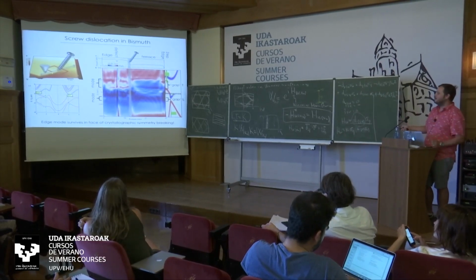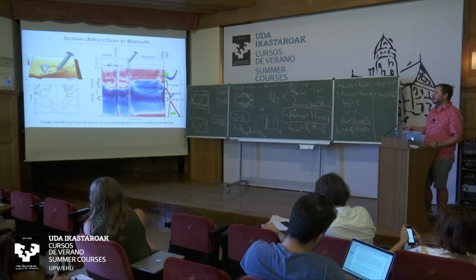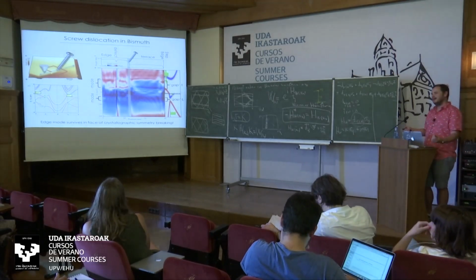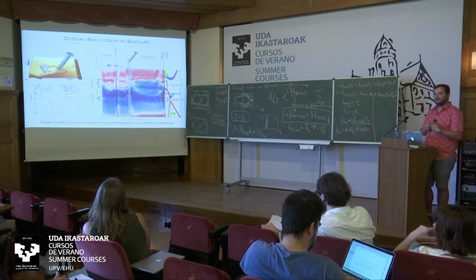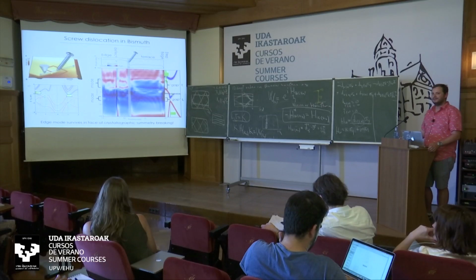We will look at this L gap, but most importantly, what we see is that this edge mode survives very happily down to the last atom where the screw dislocation resides. We don't see any signature of gradual gapping out, as if sensing some strong scatterer ahead of it, which possibly means that it goes into it.